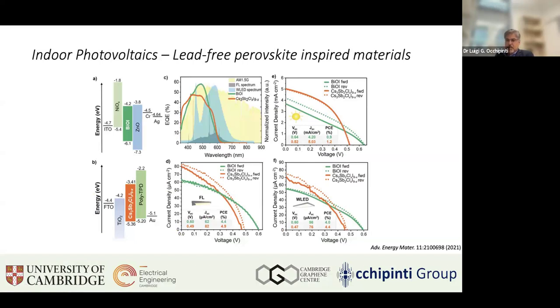And in this publication with Judith Driscoll at Cambridge and Vincenzo Pecunia and Robert Hoye, we reviewed the different lead-free perovskite-inspired absorbers for indoor photovoltaic, and investigated two classes of materials, one based on bismuth and the other based on antimony compounds, which have lower toxicity than lead-based compounds. Just to put things into context, for what concerns bismuth, there has been very little evidence of toxicity. So bismuth is known as the green element to some extent, and even the growth process is using non-hazardous precursors.